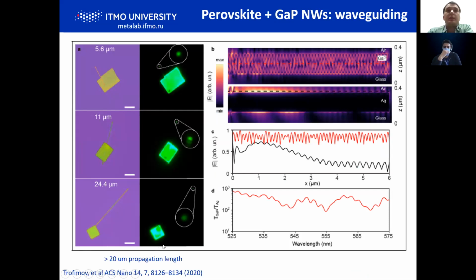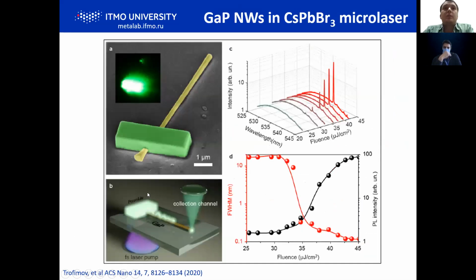You see here that in the regime of photoluminescence, we have very good propagation, almost no losses, and waveguiding in this range, even in the visible range, almost without losses. This is a comparison with a similar system published previously with a silver plasmonic waveguide, but the performance of this metal nanowaveguide is much worse as compared with gallium phosphide, as there are no losses for this material in this range. So these are some examples. Now here it is in the lasing regime, when we pump it strongly with femtosecond laser pulses.